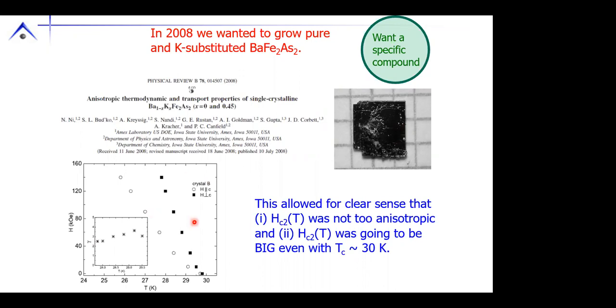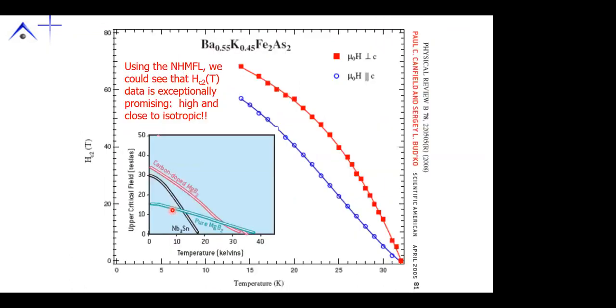So we immediately measured HC2. We can see that for up to 14 Tesla, we're suppressing TC only by a tiny amount. So we know that there are going to be very large HC2s. In addition, we have a fairly modest anisotropy. So with these data, we were able to immediately go to the National High Magnetic Field Laboratory and measure it to much higher fields. And we can see that we have A, very large HC2s, B, decreasing anisotropy.